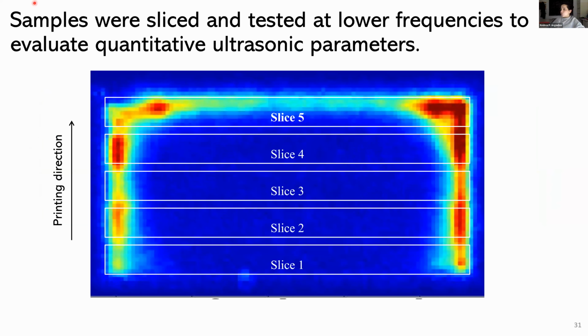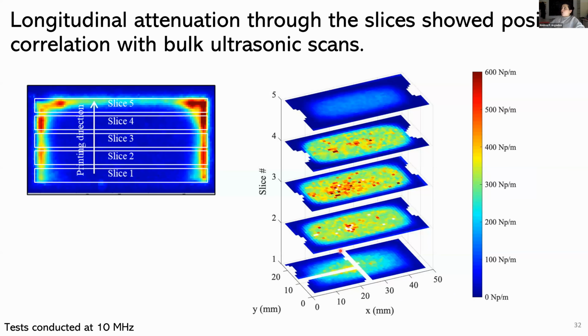So the samples were sectioned something like this. You have the printing direction, and then the slices just cut across as we go through the depth of the sample. Now, when we cut up these samples, we expected that porosity was going to be the dominating factor. You know, that's the name of the game when it comes to additive. Porosity seems to be that primary issue.